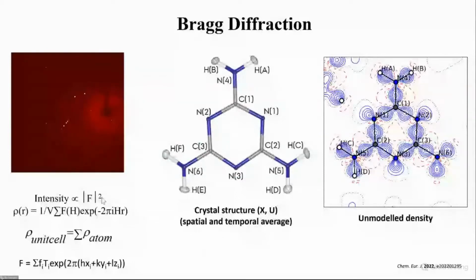So the model we all use in Bragg crystallography is that we say that the unit cell is made up of atoms. And if these are spherical atoms, we can then write this usual structure factor expression that's well known and behind all the millions of structures that have been solved. So this is how it looks when you have a result in crystallography, right? You have the average atomic positions and the thermal vibrations. And so what you see here is a spatial and temporal average of the crystal structure.